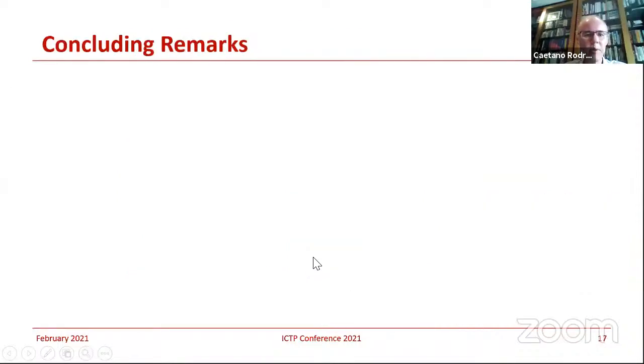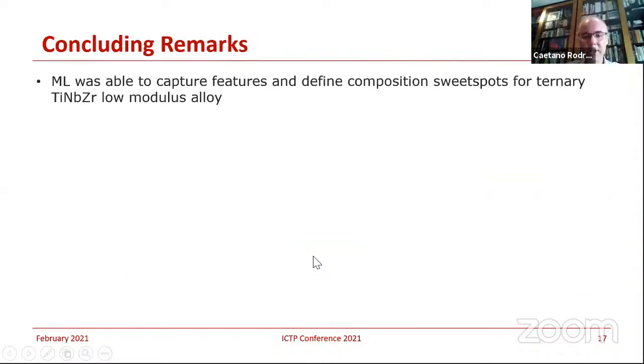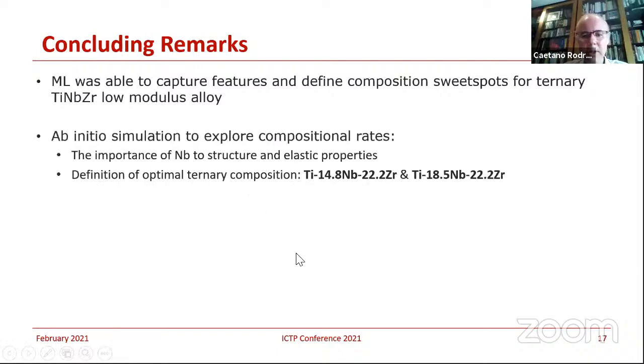Now, just as concluding remarks, the machine learning was able to capture the features, define a composition sweet spot, and figure out a low modulus alloy. The ab-initio calculation allowed us to explore the composition ranges. Here in particular, you see the importance of niobium to the structure and the elastic properties, and you could get optimal ternary compositions for those applications.